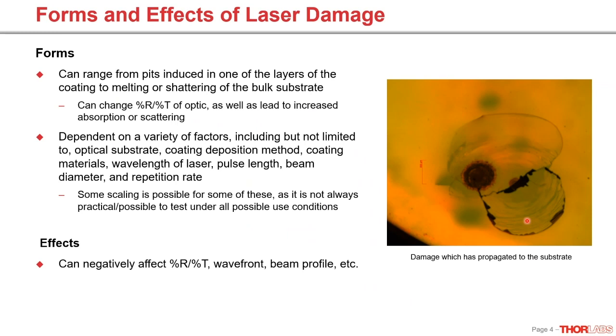Any of these, anything like that, pits, cracking, shattering, can change reflectance or transmission characteristics of your optics, which tends to be something you want to avoid, or it can lead to an increased absorption or scattering, which again is something you want to avoid. And as for what this is dependent on, it's a very large variety of factors. I have some of those listed there, and it's influenced by the substrate that you're using, the coating deposition method, the coating materials, and then all the characteristics of your laser. So there's a lot to consider here.